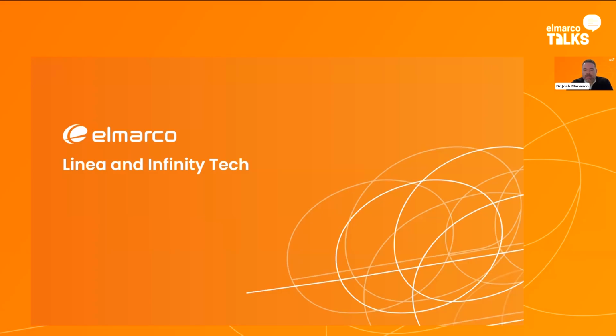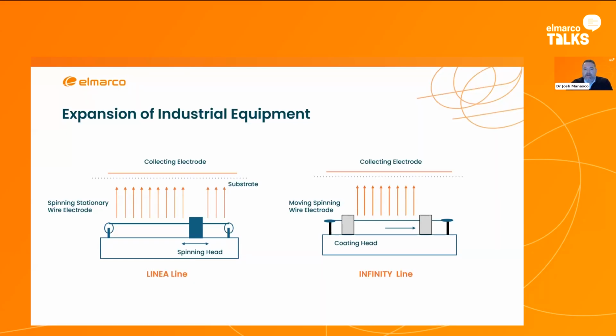So just to talk a little bit about the Linea technology and the infinity technology, we showed this image before where the coating head is moving back and forth and coating a wire. And when it coats the wire, then we have an electric field. You form the jets along the wire, you spin and you coat. In this case, we're coating continuously by moving a coating head through the process. Well, and that's the Linea technology.